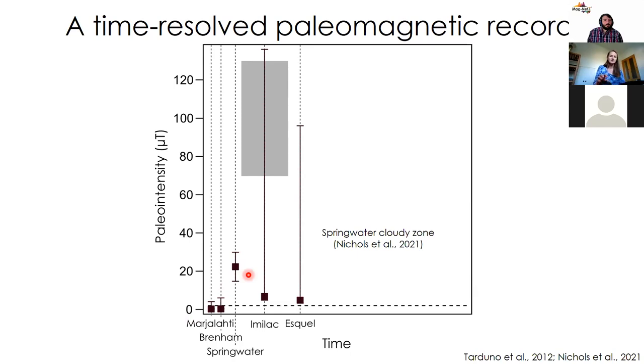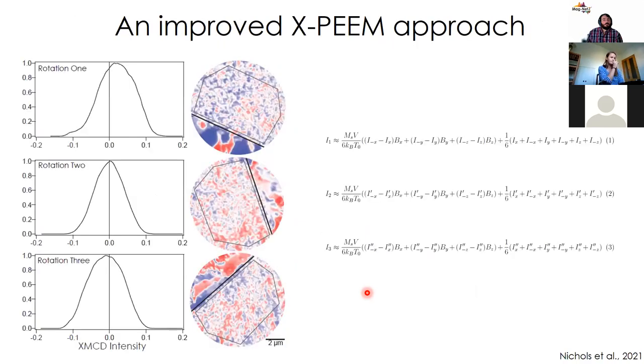And the thing you'll probably notice here is that the error bars for Springwater are significantly smaller than they are for Imilac and Esquel. This is much, much better constrained. And the reason for that is because we significantly improved and developed our method for extracting paleointensities from the cloudy zone over the years. So again, I'm not going to go into this in a huge amount of detail, but the method we use is X-PEEM, which is X-ray photoemission electron microscopy. So it's a synchrotron technique. And essentially what it allows us to do is image the direction of magnetization in a polished metallic surface.